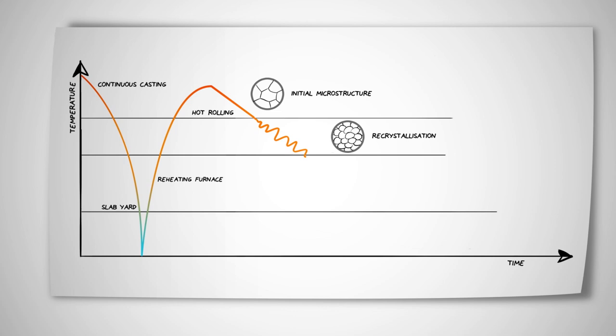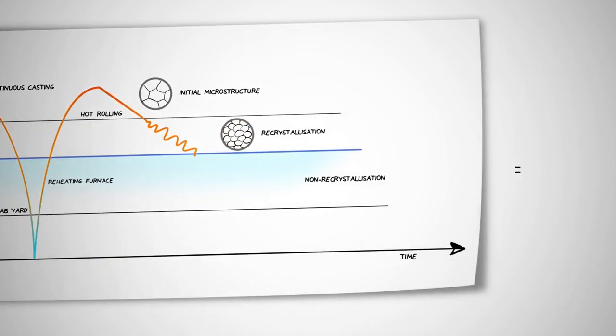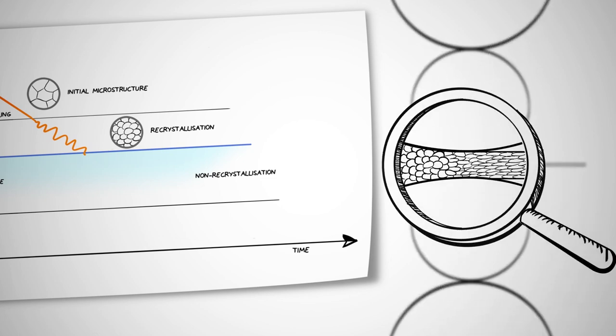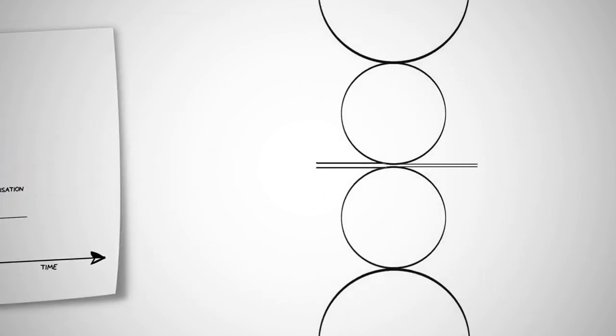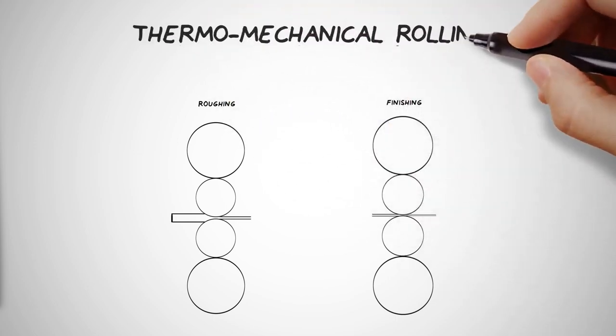However, recrystallization only occurs above a certain temperature, which is called the non-recrystallization temperature. Below this temperature, the microalloying elements in the solution are transformed into precipitates, which are small, hard particles in the steel matrix that hinder further recrystallization. The second rolling step is performed below the non-recrystallization temperature in order to achieve a flat pancake-like shape as a basis for a fine-grained structure after cooling. This is called thermomechanical rolling.